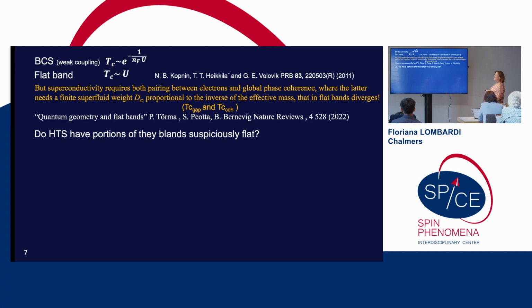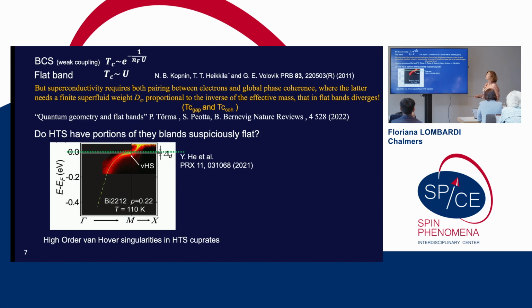So, looking at all these evolving fields, what about HTS? Do they have portions of flat band that are suspiciously flat? And indeed, they have. We have also seen from the talk of Claudia that there are other systems with this van Hove singularity at this point. And if you read papers 30 years old, they did think about the flatness here in the 0-pi direction as a possible origin of HTS superconductivity. Nevertheless, why was this thing abandoned? Because usually this van Hove singularity becomes closer and closer to the Fermi level when you go to the overdoped, so when you are reducing the superconductivity, and this is one of the reasons somehow it was abandoned.